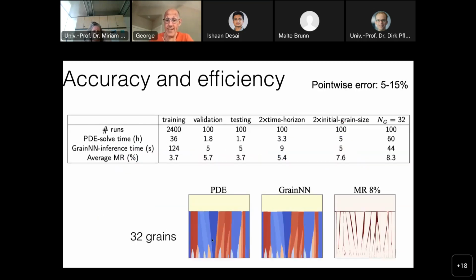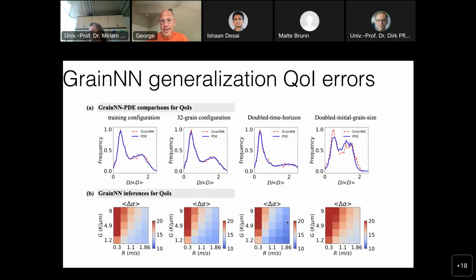But now I want to emphasize that predicting point-wise voxel is both very hard and not our goal, but also kind of meaningless, right? Because we don't really know the exact initial conditions. So there's no point of doing super accurate calculations. We want to be able to sample, and what we really care is what is the probability distribution. So if we do some calculations and we compute several times and then we do averages, so for example here what we look at is the distribution of the grain size normalized to the average grain size. So this is the histogram or the distribution of the grain size, and you can see the dotted is the neural network, and the PDE. So we can capture the distributions extremely accurately for out of distribution, double horizon, and in the initial grain size, actually the size, there is some discrepancy that may or may not be significant.